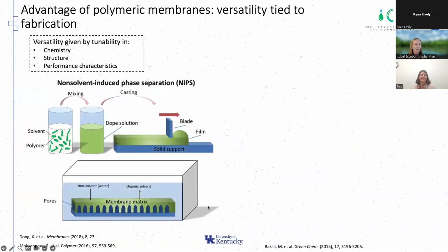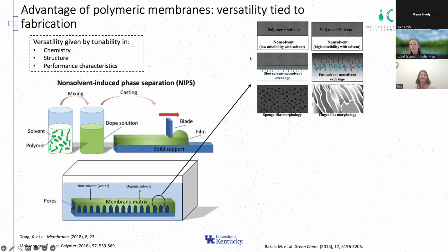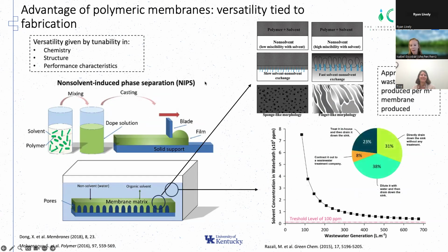So again, we use NIPS because it's versatile, it gives us a lot of power over chemistry, and it gives us a lot of power to tune the membrane performance. In this, we have the polymer and solvent. We can put a substrate under, a polymer support, or make it a freestanding membrane. We can tune the evaporation time. We can use a combination of polymers and solvents in order to increase or decrease the precipitation time and make our pores more sponge-like or more finger-like, all in the choice of polymer and solvent and in how fast the phase inversion occurs. So this, again, gives NIPS a lot of power.